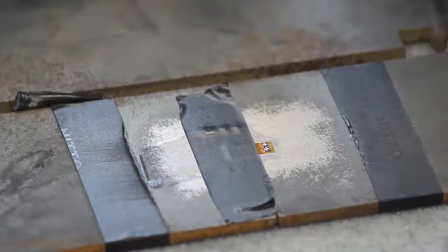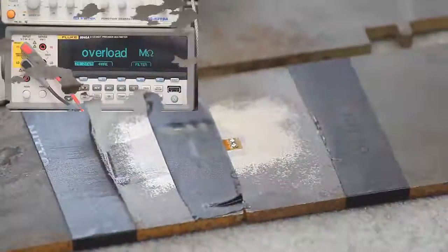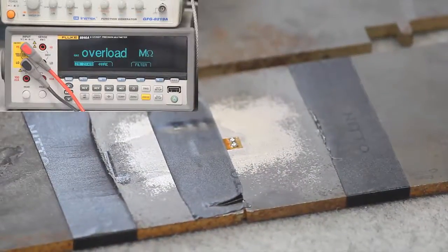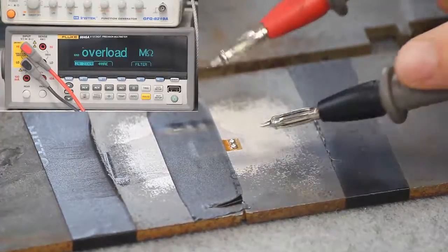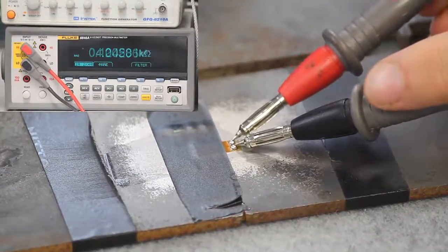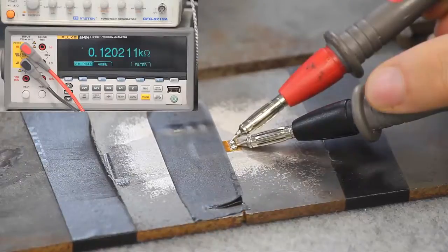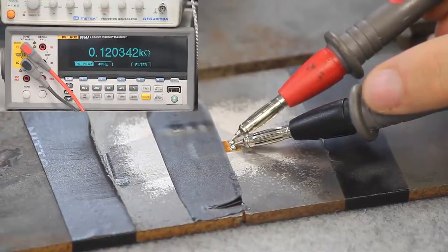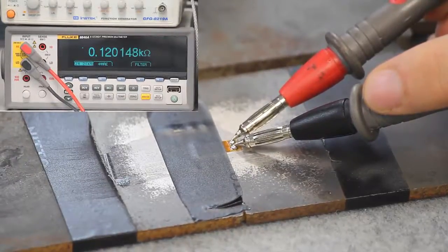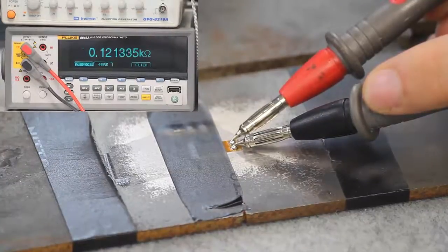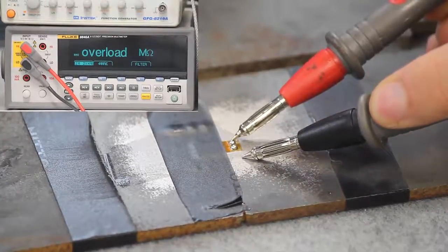Allow some time for the strain gauge to cool down. At this point, it is a good idea to check the strain gauge with a multimeter. Check that the resistance is still approximately the correct value between the two pads. Also check the resistance between the beam itself and the two pads. On rare occasions, it is possible for solder to melt through the pad and attach to the beam, causing a short circuit.